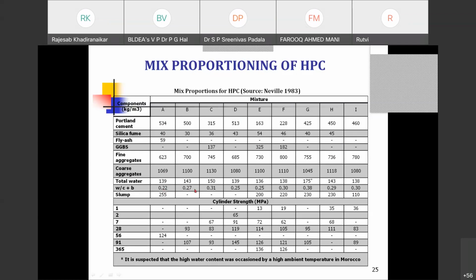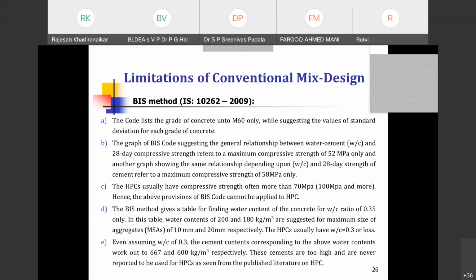This is the main thing: we have seen the two techniques of reducing the water binder ratio, 0.22, 0.27, and so on. So they have reduced the water binder ratio, and by virtue of that, they were able to get a high strength. So coming to our BIS method, that is IS 10262 2009.